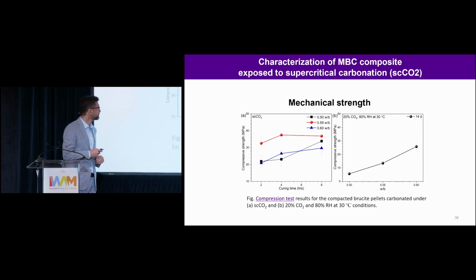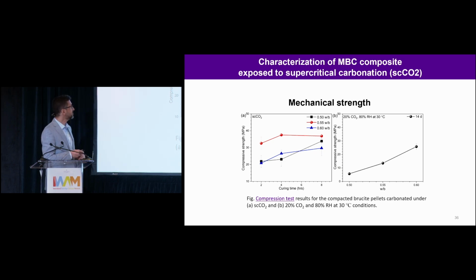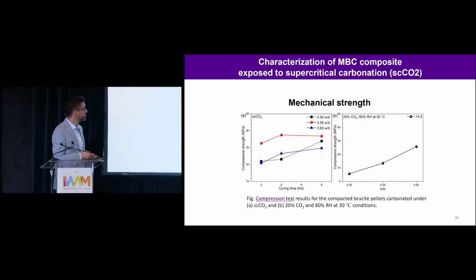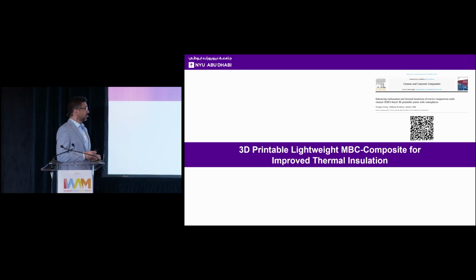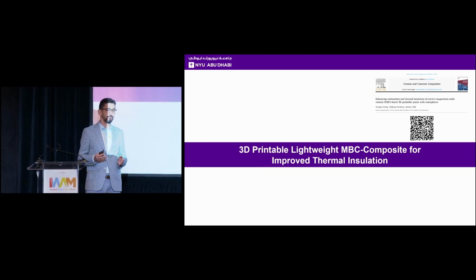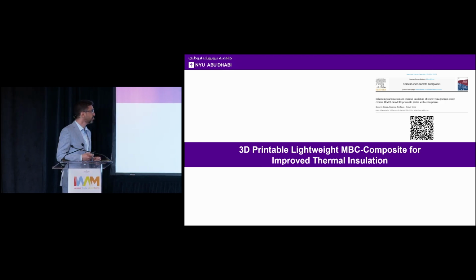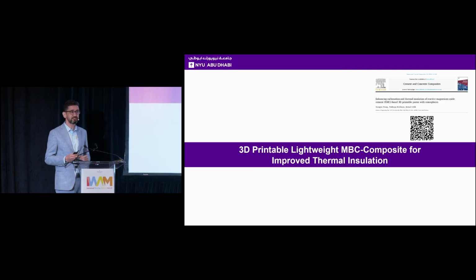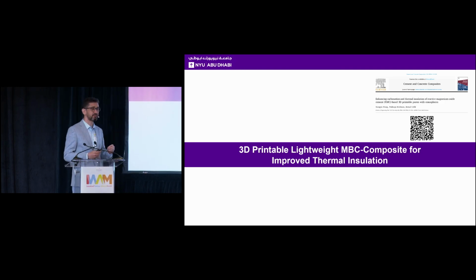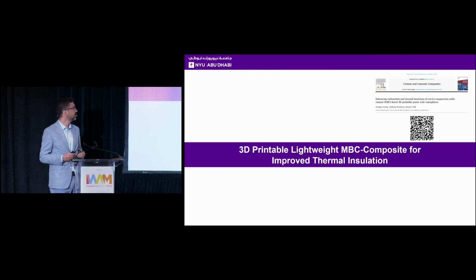Here we see another version of this mechanical strength development with respect to water to binder ratio. At 14 days, the one cured in the environmental chamber reaches around 30 megapascal, and the one cured in the supercritical reactor reaches much higher strength. And in this region, 3D printing is also another hot topic, and we'd like to see how 3D printable this material is and how adding cenospheres, a byproduct of coal combustion power plants, will be useful to improve the thermal insulation of this structure and produce a lightweight composite.